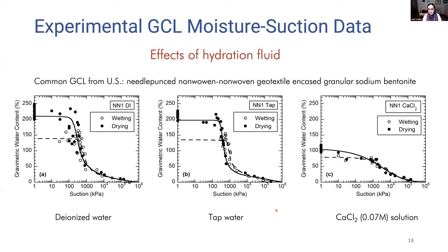We did some experimental analysis to establish these relationships. In this case, we're looking at water content versus suction plots for a given geosynthetic clay material. This is a product from the US, a needle-punched, nonwoven, nonwoven geotextile with a granular sodium bentonite. NN1 was the designation that we used for this material. In this case, these graphics are for gravimetric water content versus suction. And the formulation that we used actually is not the Van Genuchten relationship, but the Fredlund and Xing relationship. In this paper that we analyzed this material, we also have the Van Genuchten parameters. Also, for the gravimetric water content analysis, the Fredlund and Xing analysis is more appropriate.